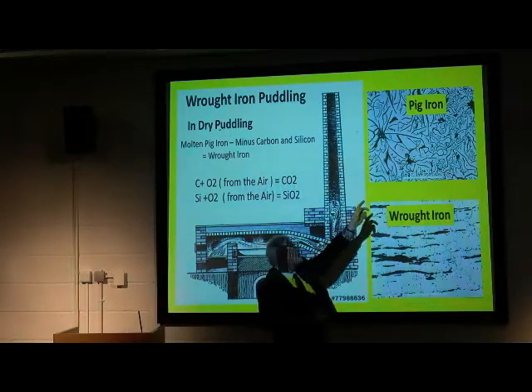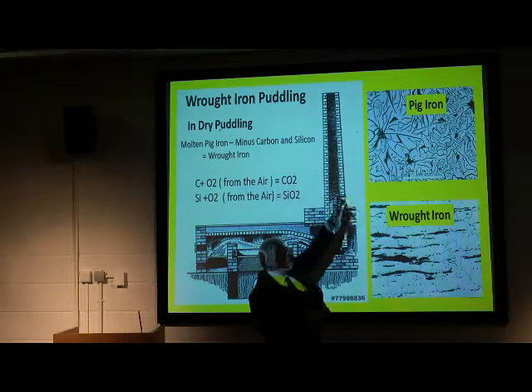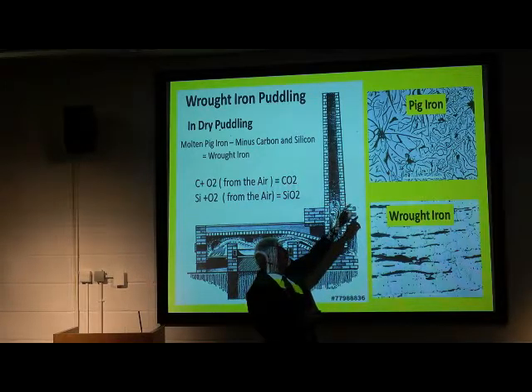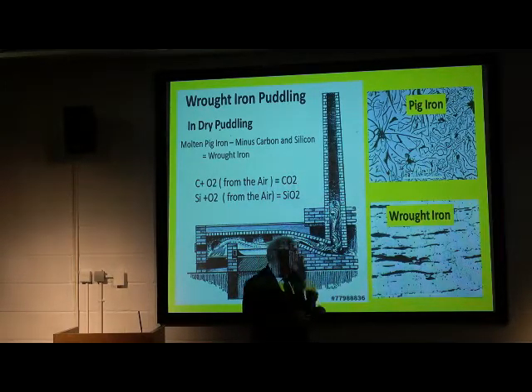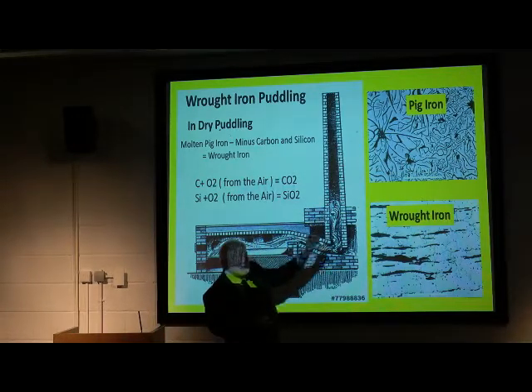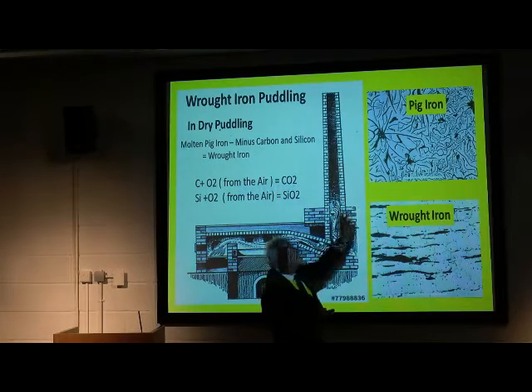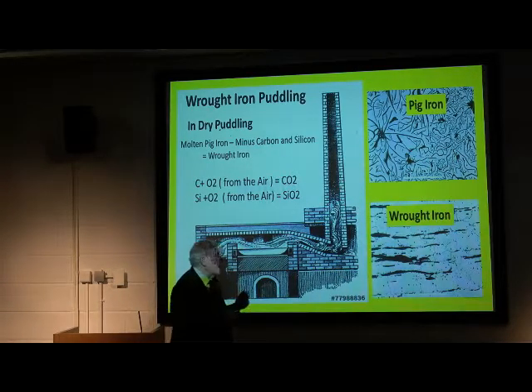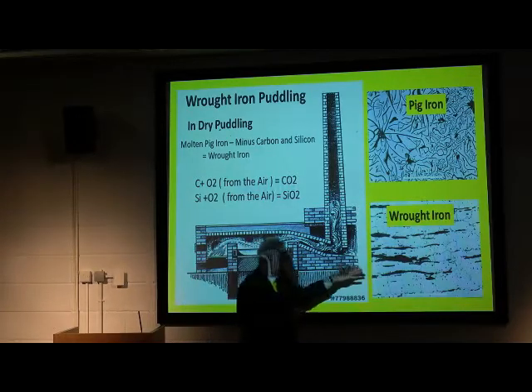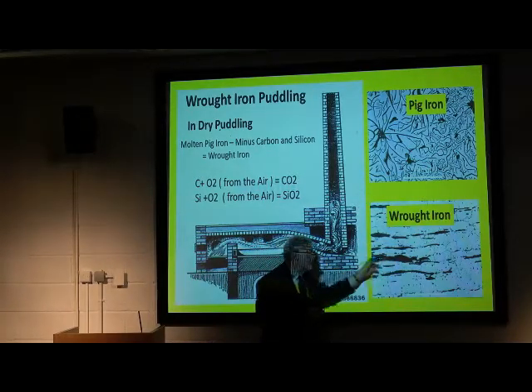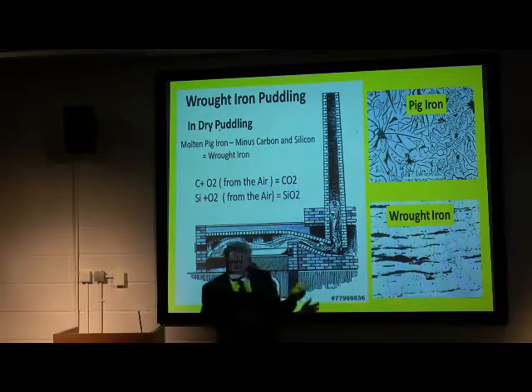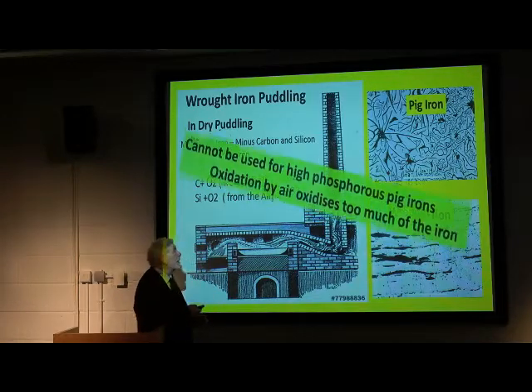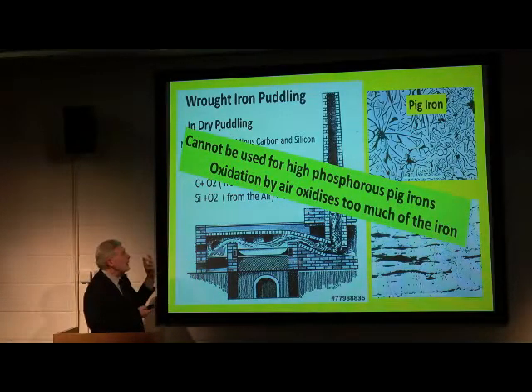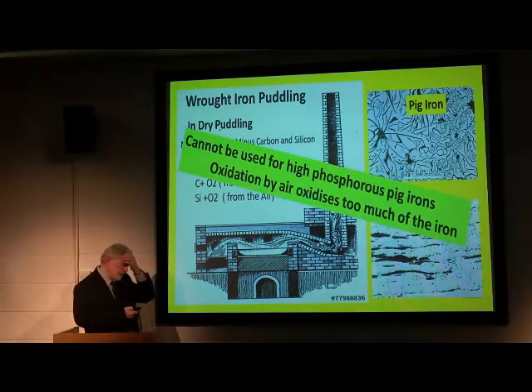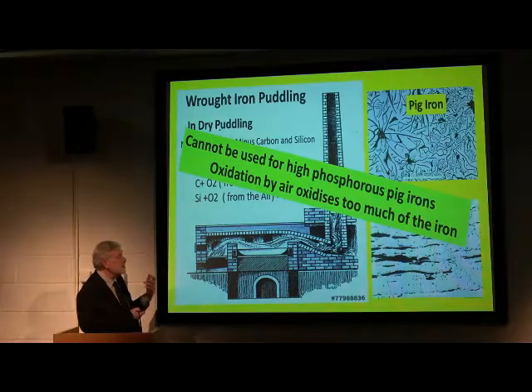Pig iron starts off with all of these funny spidery looking things, which are really flakes of graphite, which have been sectioned. The graphite makes the iron very brittle because cracks run through the iron along the flakes, and that's why it is very brittle. But at the end of the process, you come up with wrought iron, you've got rid of all the carbon. This black stuff looks bad, but it's pretty innocuous. It's just layers of slag. But you can't use the dry puddling process here, because you just oxidize too much of the iron.